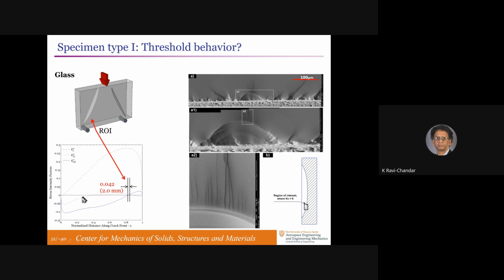Mode 2 stress intensity factor is given by this. In this region of the black box, the mode 2 stress intensity factor is very nearly 0. So we've taken that out of consideration. The mode 3 stress intensity factor is given by this line. And that's the interesting one, because what we've done is make the mode 3 value go from a negative number to a positive number over that length, meaning it crosses 0. So in one test, we can look at what happens at different mode 3 to mode 1 ratio.